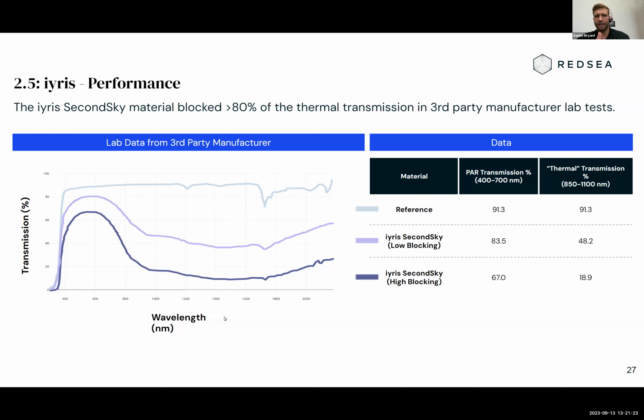The interesting thing that we're finding now is that, broadly speaking, the closer to the equator or the hotter the region, you probably want more blocking, because you usually have lots of PAR, so you don't mind the sacrifice, and you really want this because you have lots of temperature buildup. But we're finding that even in regions such as Southern Europe, in certain crops such as peppers, you can go quite aggressive and you don't get any penalty and you start to get some upsides. So this is the main effect that we're seeing in our films: near infrared blocking in this region.